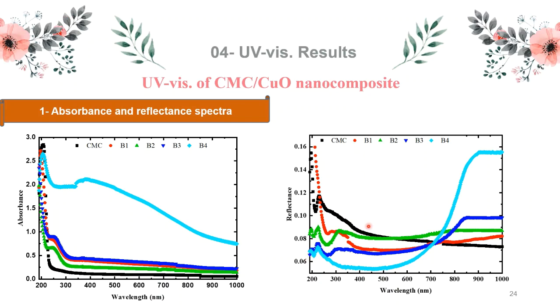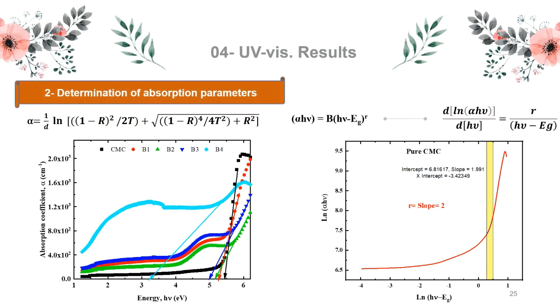However, this figure presents the spectral distribution of optical reflectance for pure CMC and CMC doped with different concentrations of copper oxide nanoparticles. The figure shows that the reflectance of pure CMC decreased sharply at shorter wavelengths and shows a single peak in the UV region, whereas the reflectance of the CMC copper oxide nanocomposite films drops somewhat with increasing wavelengths. The reflectance value increases in this region, which may be associated with the increasing roughness of the films due to the addition of copper oxide nanoparticles, which increases light scattering. Another reason for this increase in reflectance is the addition of crystalline nanocomposites, which increases reflectance along grain boundaries.